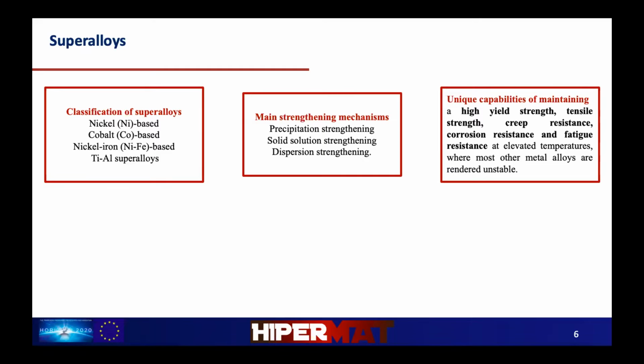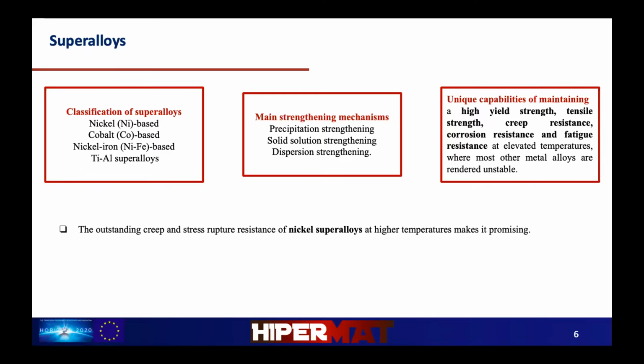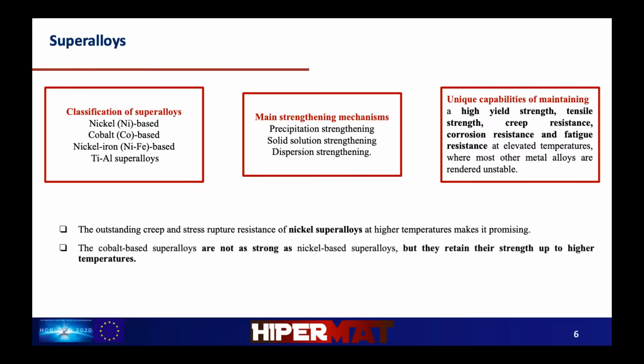resistance at elevated temperature. It is great to note that the outstanding creep and stress rupture resistance of nickel superalloys at high temperatures make them very promising, whereas cobalt-based superalloys are not as strong as nickel-based superalloys, but they retain their strength up to high temperatures. Inconel, Waspaloy, Rene alloys, and Haynes alloys are a few of the very well-known examples of superalloys.